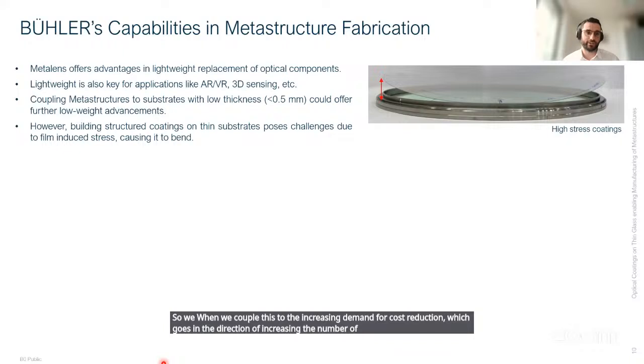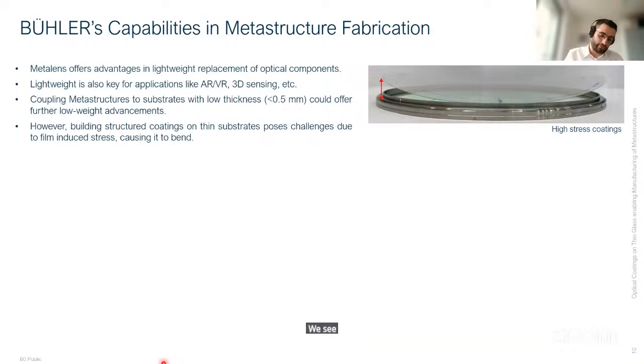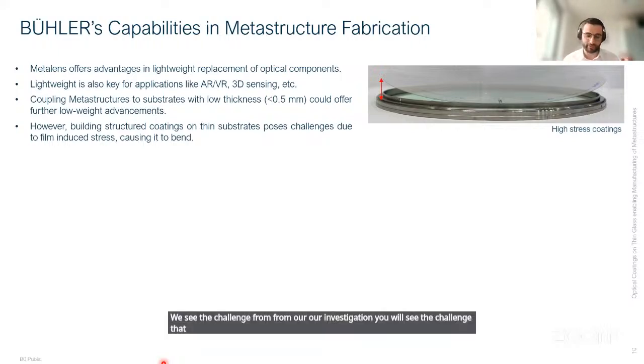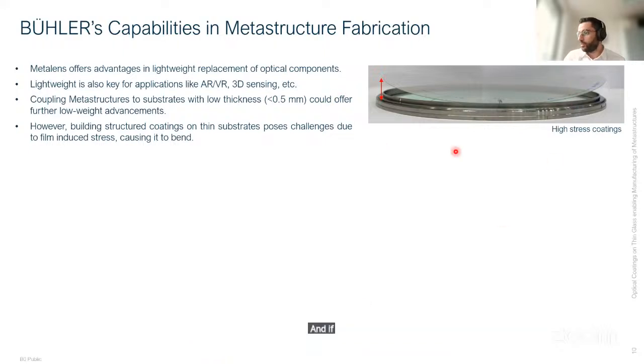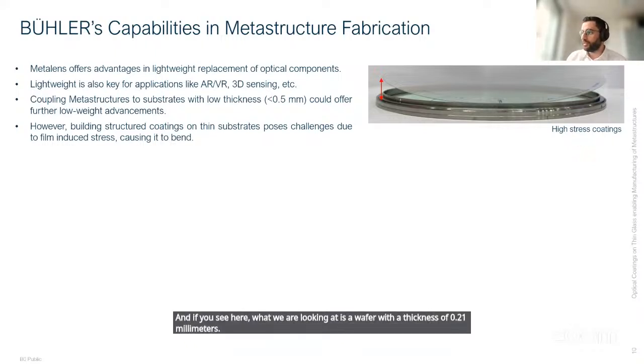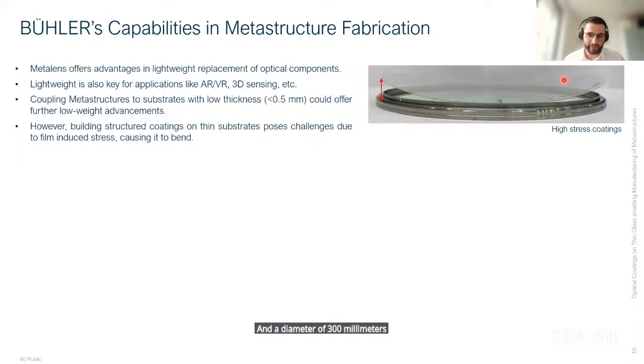of products that can be used in a wafer, meaning increasing the wafer size, we see the challenge from our investigation. We see the challenge that if we increase the wafer size and we still build the traditional optics and the traditional structures on the wafers with a certain thickness, we start seeing problems arising from the type of stress that coatings can give rise to. And if you see here, what we are looking at is a wafer with a thickness of 0.21 millimeters and a diameter of 300 millimeters. So a traditional wafer size, but a much smaller thickness.